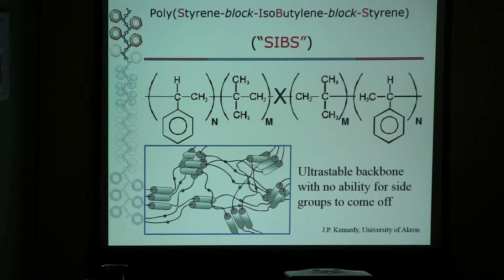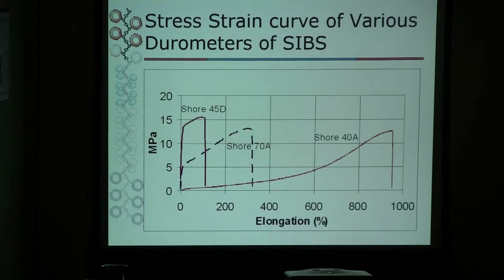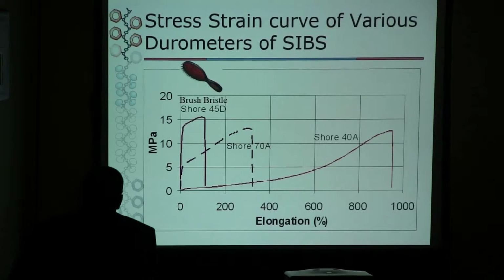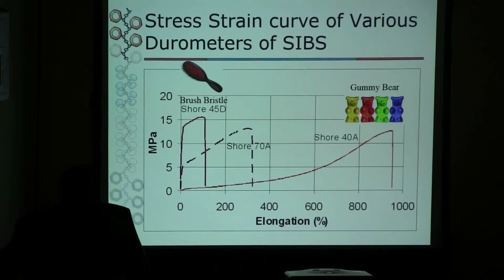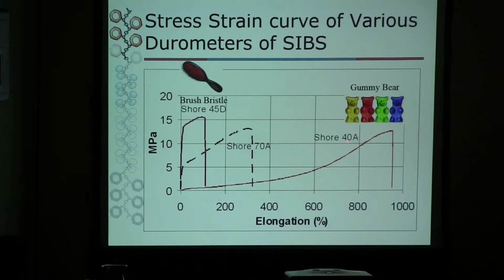another block of polystyrene. So what's neat about this is there are no cleavable groups on the backbone, and there's no cleavable groups on the sides of the polymer. And we found that the tissue interface and the biocompatibility was very different than what we've seen before. Now, by controlling the amount of polystyrene, if you put a lot of glass in or a lot of styrene, you have a very hard material, and it's like brush bristles. If you put in very little styrene, you can make things like gummy bears. And why am I saying gummy bears? Because you'll see when I talk a little later about intraocular lenses, you can flow these fully formed lenses through a small cannula.